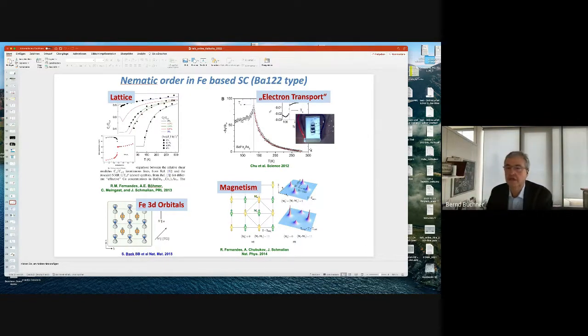You have tiny strain. But here, what you see here, even the slope, so the change of the resistivity divided by the size of this strain, diverges. So you have this, and that's what people call nematic susceptibility, and the divergence of a nematic susceptibility. And this is now electronic degrees of freedom. So it's clear that lattice plays a role, orbitals in some sense play a role, magnetism plays a role, but also the electronic states. And that's the nematic order in iron-based superconductors, which is quite characteristic.